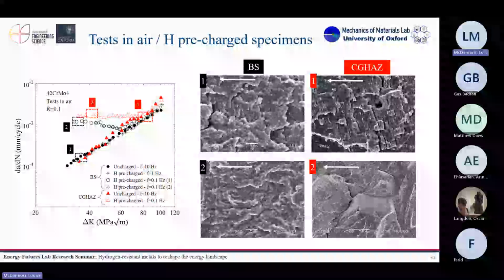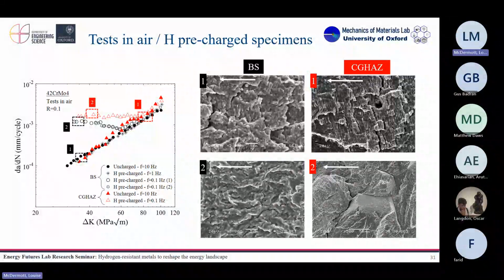Okay? So you see, the main takeaway from this slide is, okay, when we have hydrogen and we test at low frequencies, we do really see an effect. Okay, so the material is becoming more brittle, and then the crack is growing much faster. Okay, when we do fatigue.